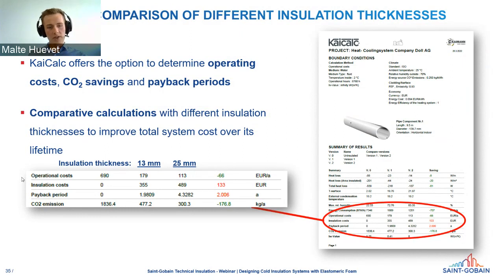There we dropped already in our operational cost from 690 euros per year to 179 euros per year. But if we would add, for example, an additional 25 millimeter insulation thickness, then we drop even below the 179, of course, and save an additional 66 euro per year, and that would result, for example, in a payback time for the thicker insulation version of 2 years. And after this time, of course, we save 66 euros annually, year by year. And this is calculated, what I forgot to mention, just with 9.4 cents. So KaiCalc offers this option also regarding CO2 savings, for example, but especially for calculating the operating times and payback times. This option is also included in KaiCalc.